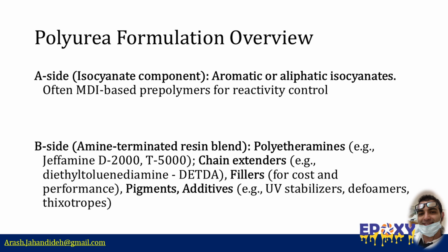Fast-reacting aromatic diamines like DETDA, or diethyltoluenediamine, are often used as a chain extender to enhance curing speed and mechanical properties. To tailor performance and reduce cost, formulators may include fillers, pigments, and specialized additives such as UV stabilizers for outdoor durability, defoamers to minimize entrapped air, and thixotropes to control sag and flow. Balancing these components is key to achieving the desired performance profile, whether it's flexibility, hardness, or chemical resistance.